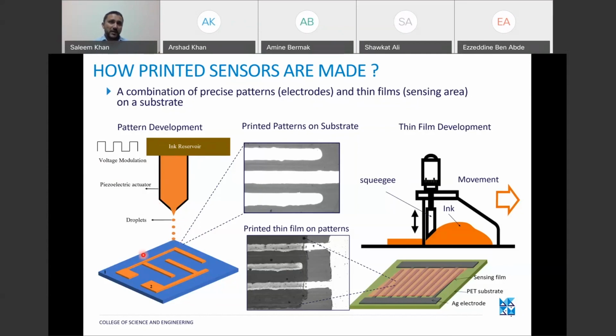And the blue color here is any arbitrary substrate, like flexible substrates. In our case, we are usually using PET plastic substrates or textile, cotton-based or paper substrates. And here the patterns are any metallic conductor. Here they are actually representing interdigital electrodes. So for interdigital electrodes, we need metal inks. These are first designed in software and then exported to the inkjet system. And the parameters are tuned and we achieve results such as these.